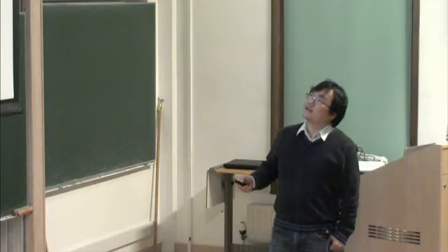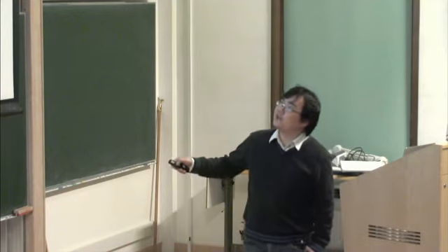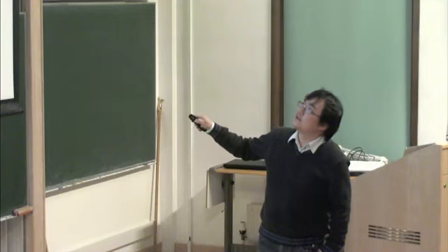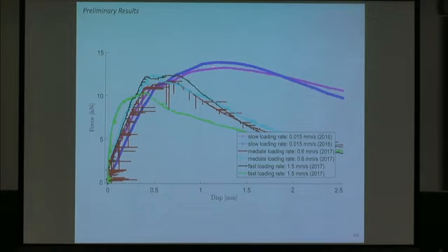Yes. And how reliable this one is, I'm not quite sure. Because if I zoom in here, it seems that these are the slow loading curves, and they look quite alike towards each other. I guess what I'm getting at is the statistical significance of this difference, knowing how variable our measurements are, almost of any kind one makes on ice. There's a number, and then there's a plus or minus some standard deviation, and there's variability.